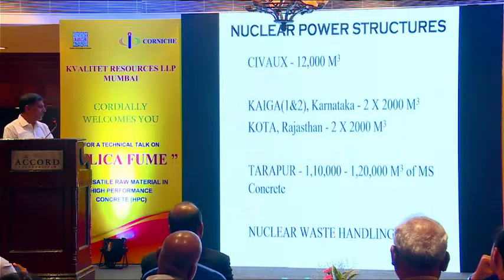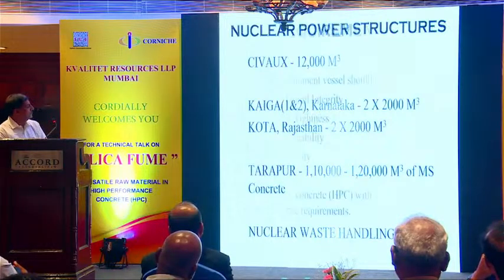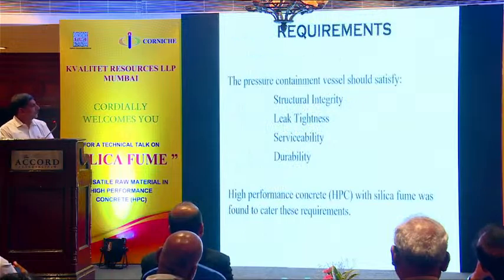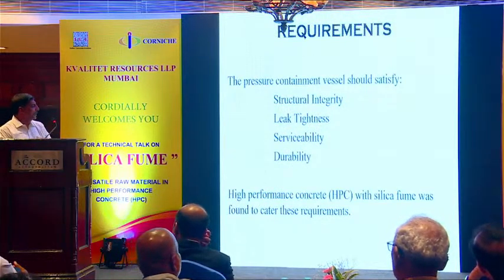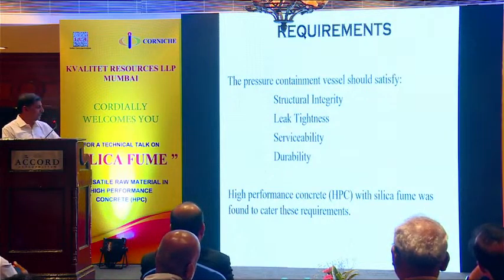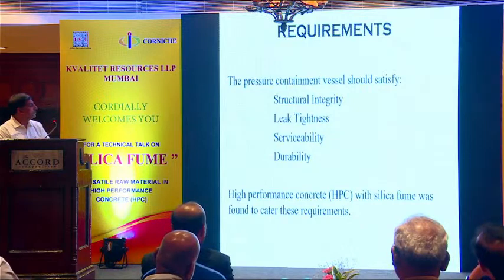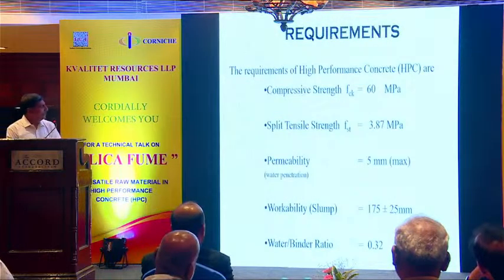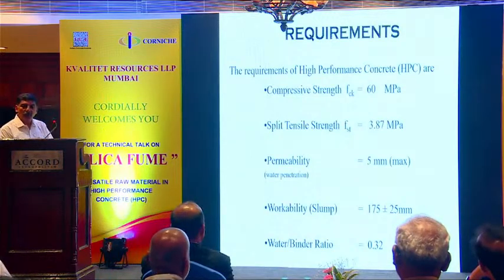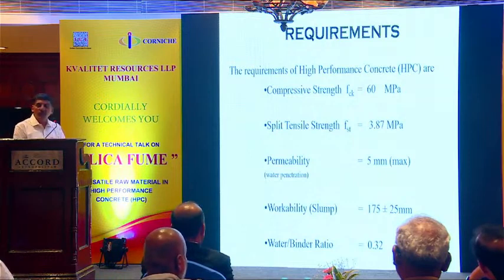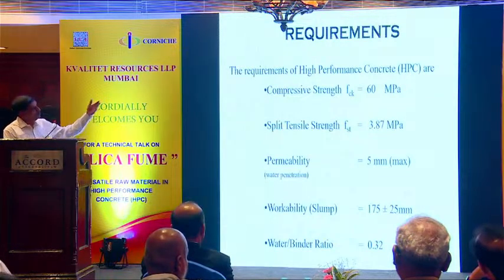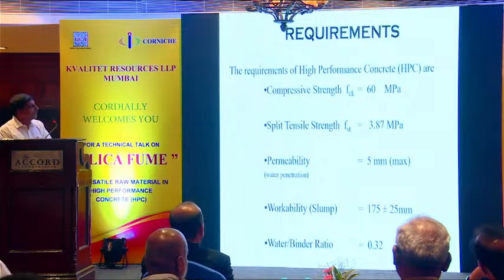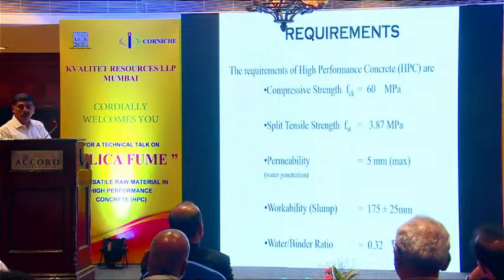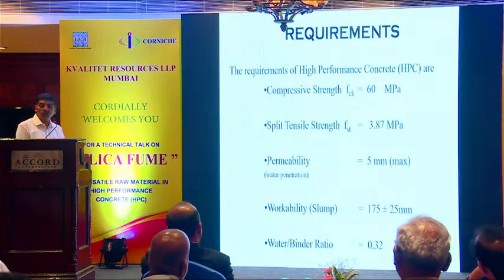And today, I think they're specifying it for nuclear waste handling systems to prevent radiation leakages. The requirements: the pressure containment vessel should satisfy structural integrity, leak tightness, serviceability, and durability. And high-performance silica fume concrete was able to cater to all these requirements. They wanted a compressive strength of 60 MPa. More than compressive strength, they wanted a split tensile strength of a minimum of 3.9 or something. By doing an M60 concrete, they ended up making M60 concrete with a mean target strength of 74, 75 megapascal, and a split tensile strength they were able to hit up to 4.5 megapascals.